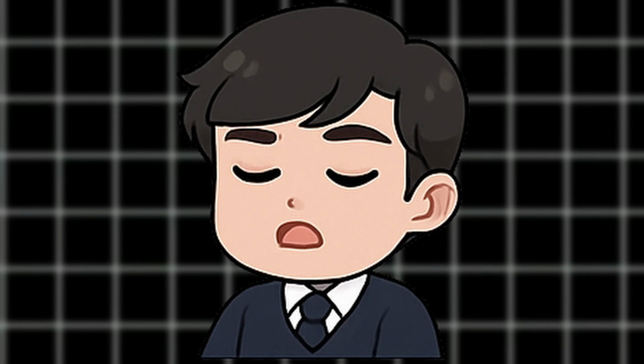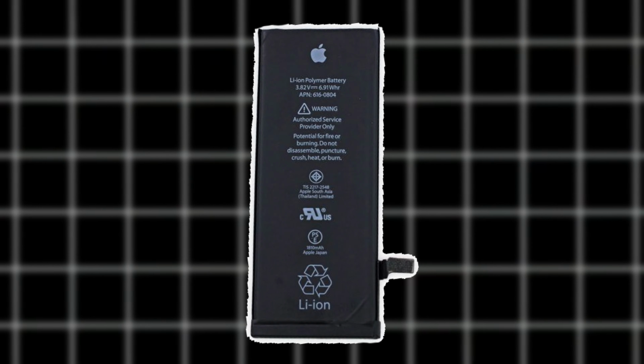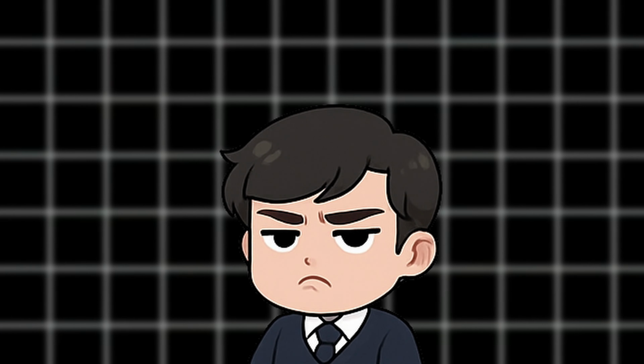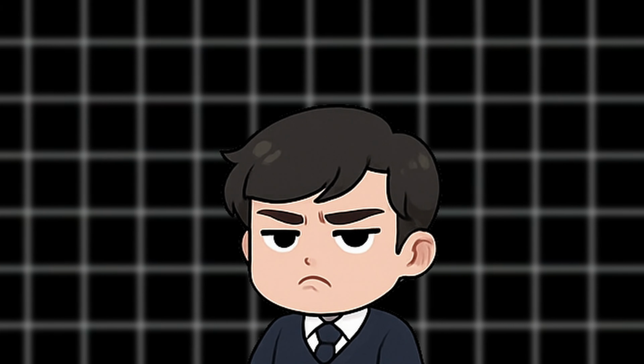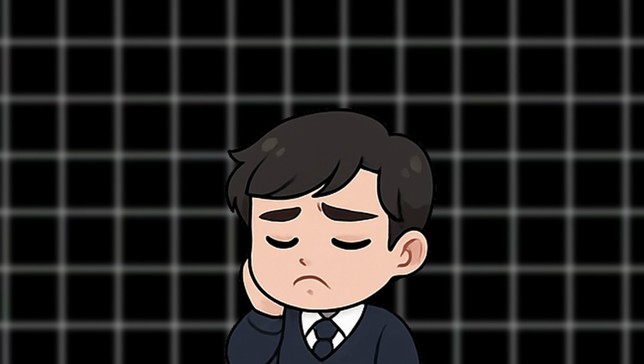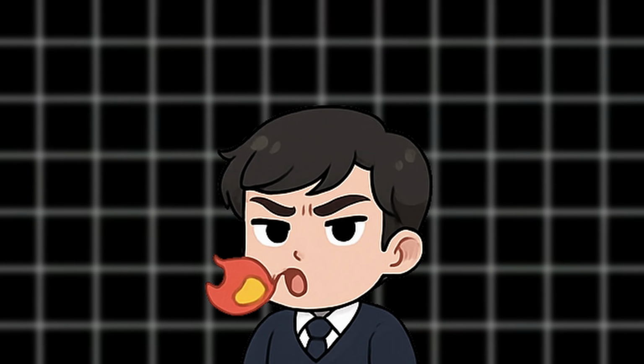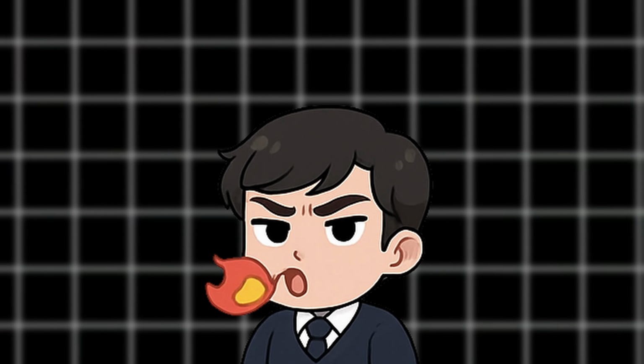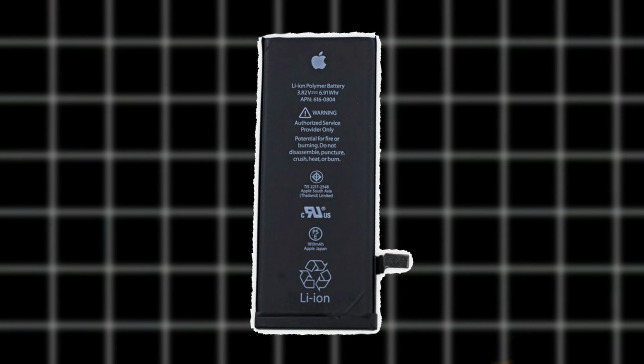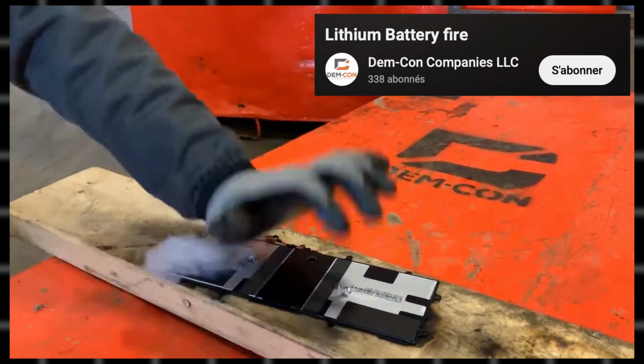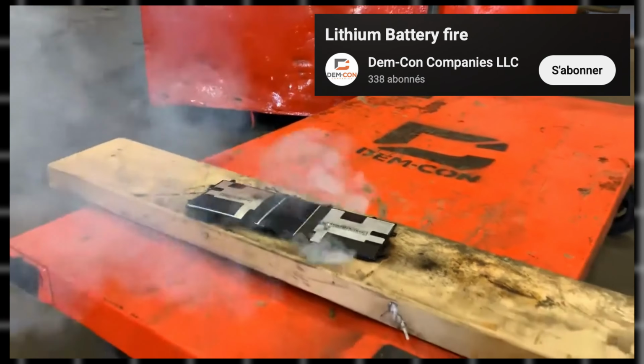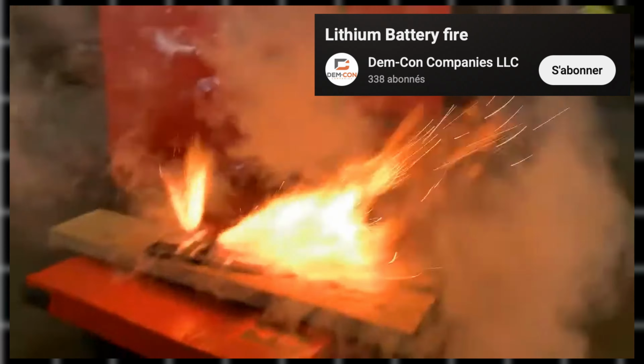High temperature. Batteries hate it. The ideal temperature is between 20 and 35 degrees, but once you go above 40 degrees, bad chemistry starts happening inside. The electrolyte becomes unstable and can react with the lithium or the binder material. If it gets too hot, this reaction becomes exothermic, meaning it generates even more heat, which can lead to thermal runaway. That's the point where a battery can literally catch fire, usually around 130 to 150 degrees, depending on the chemistry. The SEI layer also breaks down when hot, forcing it to rebuild over and over, wasting active lithium and permanently reducing capacity.